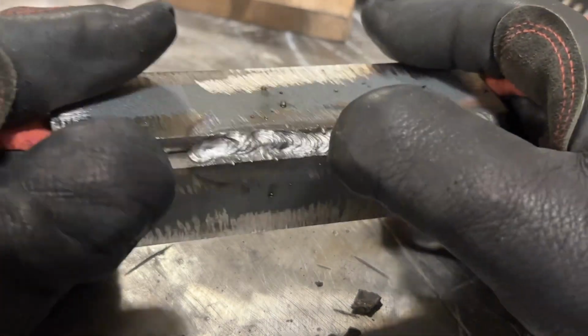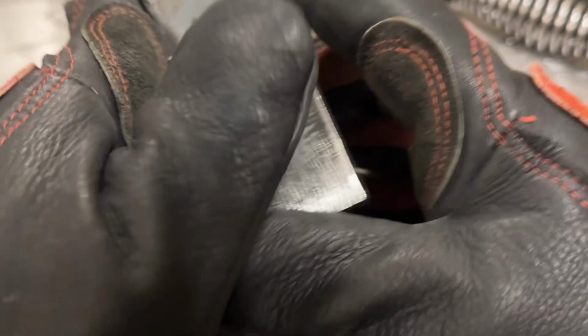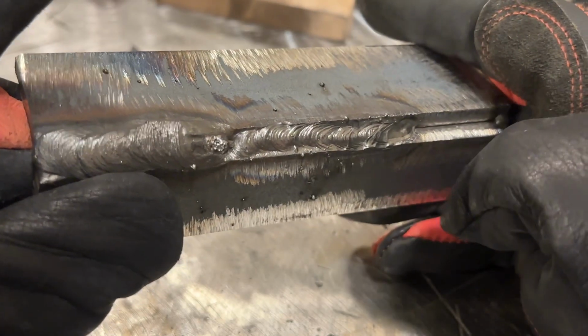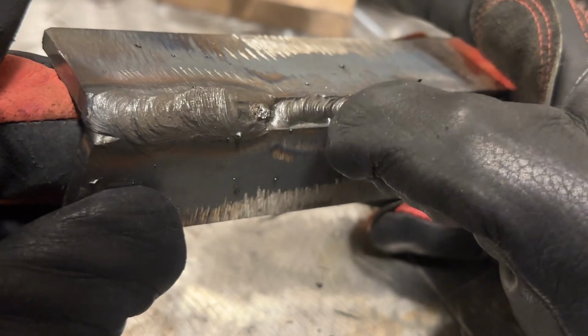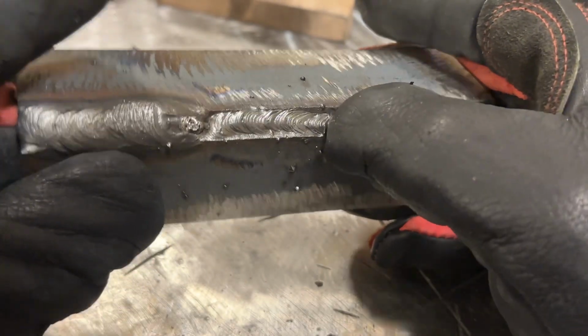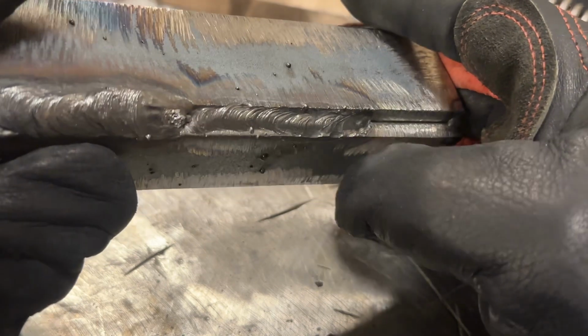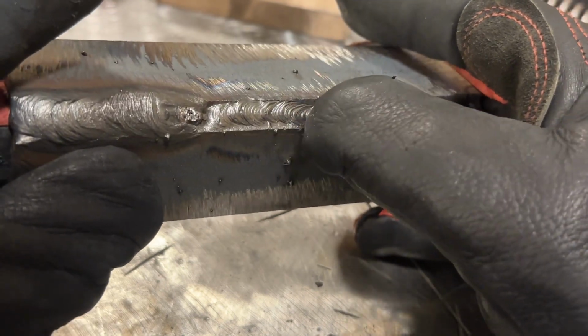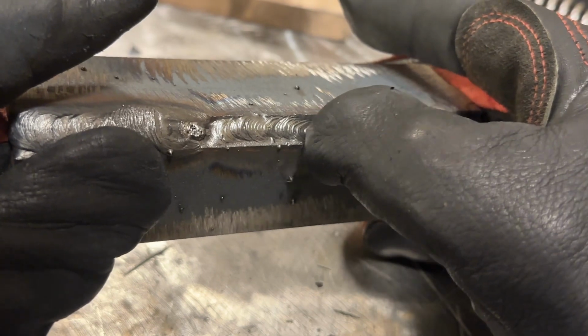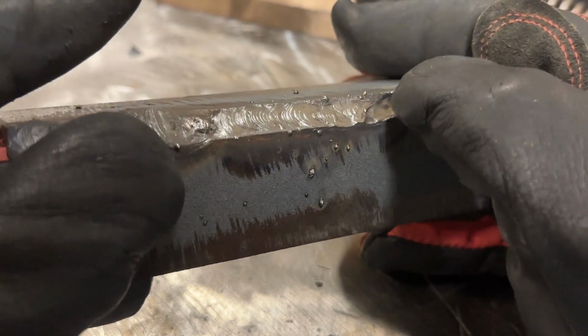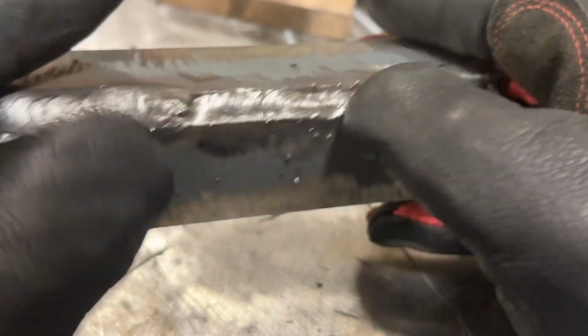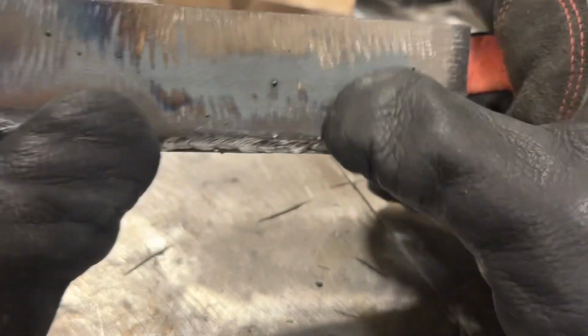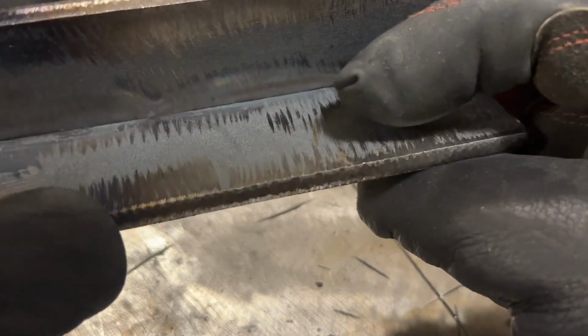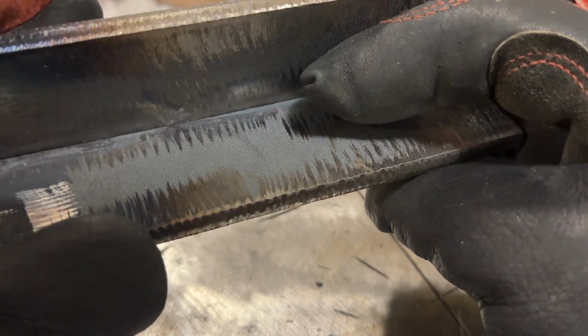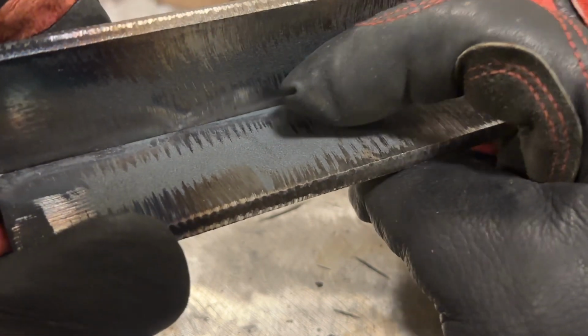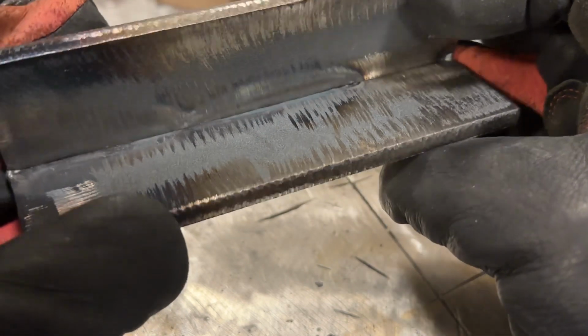So completely different results. Now ignore the spatter and all of that, but much flatter bead profile than this, much less metal deposited. Now I ran this at about 105 amps, which seems maybe a little bit hot, but my travel speed from this point on increased a little bit, and you can see how I have underfill in there. The first half of it looks really good for being flat. Now backside penetration is going to be a little bit hard for you to see on the camera, but that weld nugget is right there on the inside of that. So it's pretty much right where you want it.